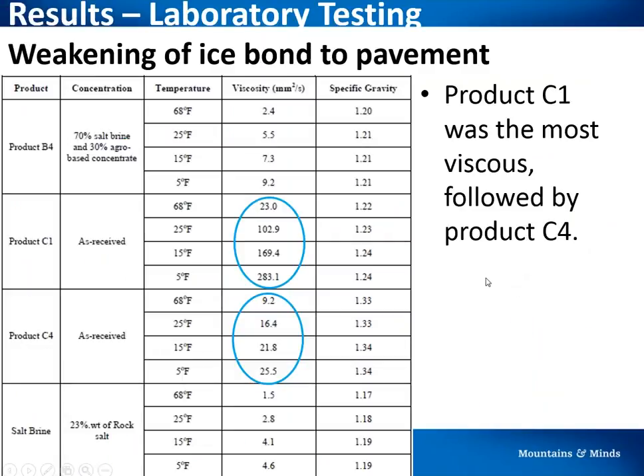One of the interesting things that came up as we were doing this testing was the fact that these agro-based products are really good anti-icers. So they weaken or prevent that ice bond to the pavement compared to salt brine alone. And why might that be true? Some early research suggested that maybe viscosity had something to do with it. So as an add-on to this project, we actually measured viscosity for those 3 products, B4, C1, and C4. And remember, product B4 is an ag-based product that's mixed with salt brine, so it has a pretty low viscosity. But products C1 and C4 were as received from the manufacturer, and they had higher, and for C1, much higher viscosities. So we were thinking that maybe viscosity had something to do with weakening that bond, or at least functioning as a better anti-icer.